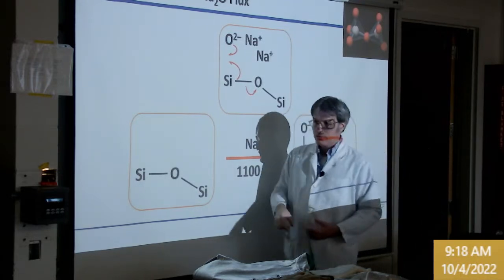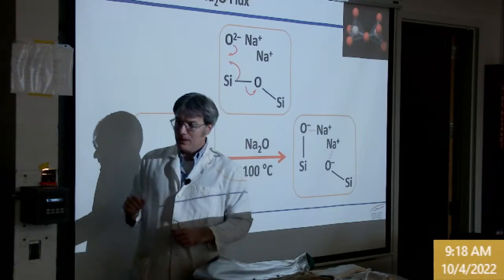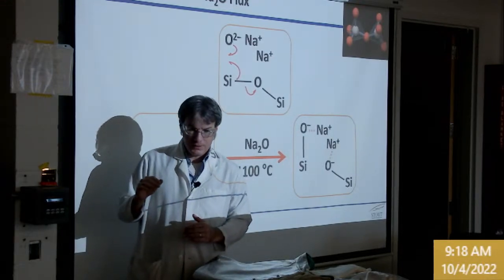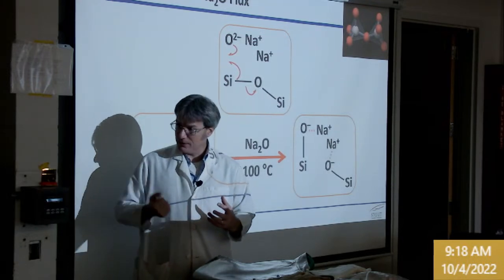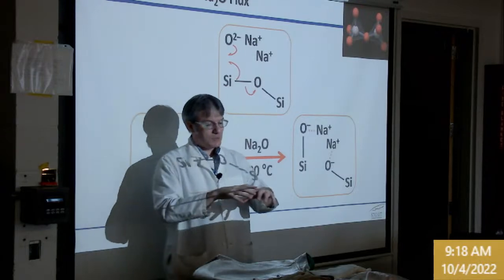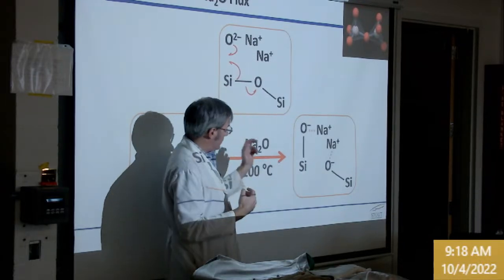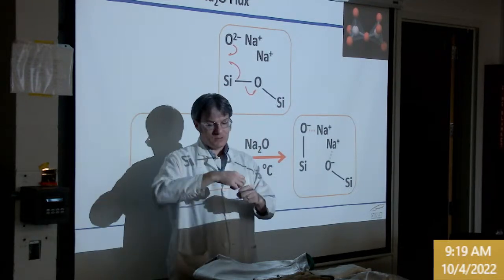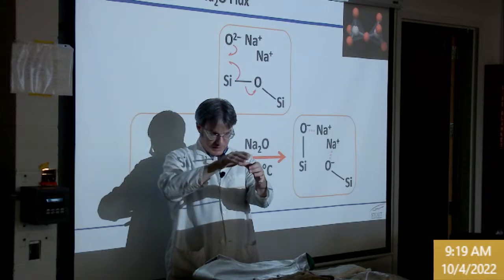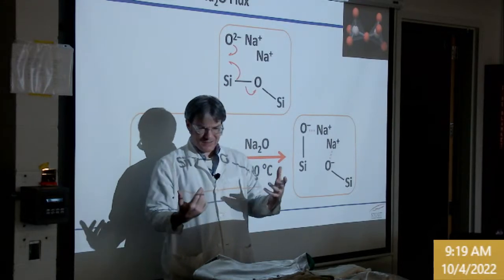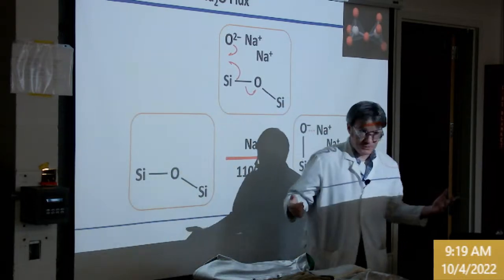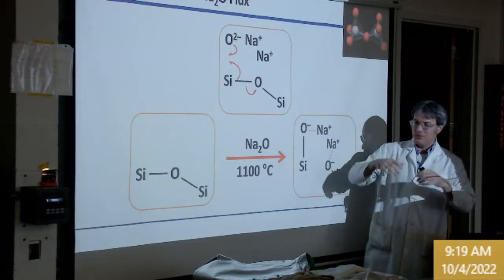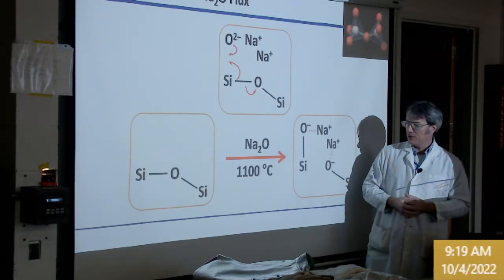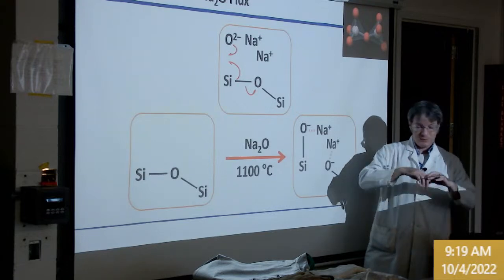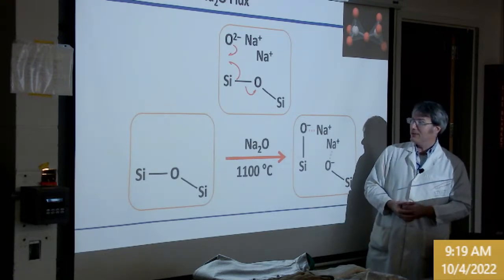So last night, when I was doing the thermal ramp for the furnace, once you get up around 1,000 degrees, you can actually hear bubbles popping in that furnace because the surface skins over with glass and it's still blowing carbon dioxide bubbles from the reaction that leads to sodium oxide. I had a crucible that actually had a glass bubble forming on top, and then it pops, and it's kind of like boiling potatoes, you know, all that kind of a foam you get on top that sort of builds up. It's kind of like that. Or enter your favorite boiling over story. But the idea is to keep enough space in the crucible to prevent it from actually boiling over, because that makes quite a mess in the furnace, because it's glass, after all.